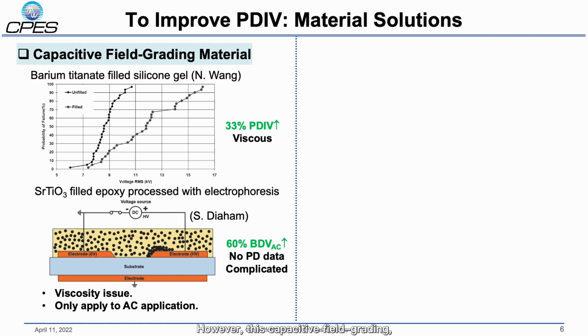However, this capacitive field grading material usually needs very high material loading to achieve high permittivity, which will make the material very viscous, and it could be a problem when you want to use it for encapsulating a real power module, because it will be easier to trap bubbles and cause partial discharge. Besides, they are only functional under AC excitations.